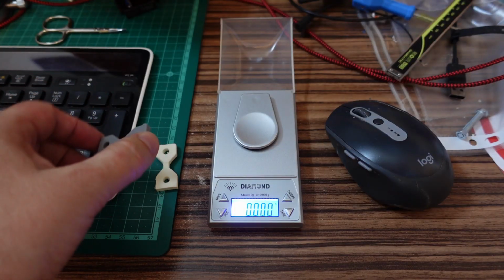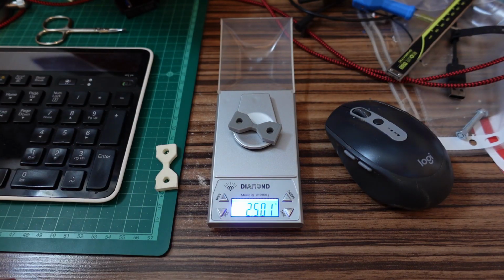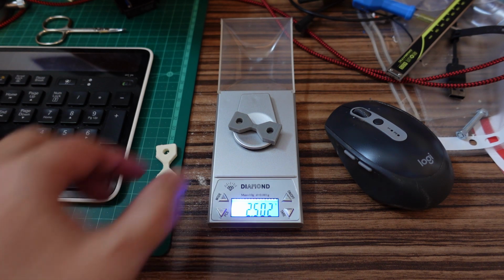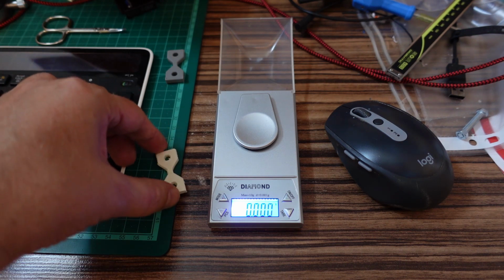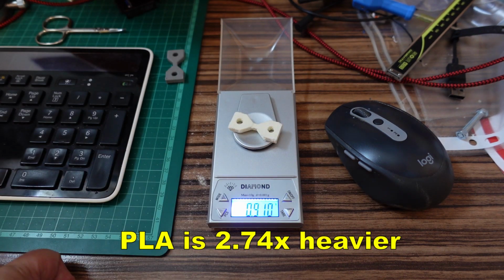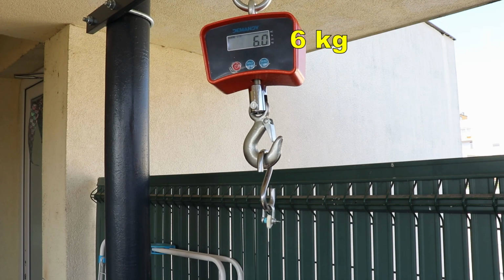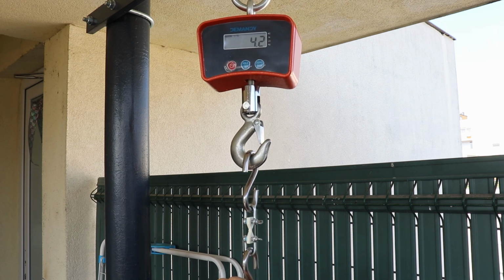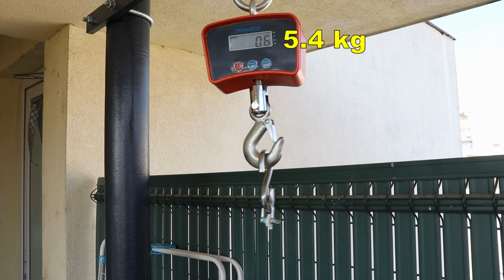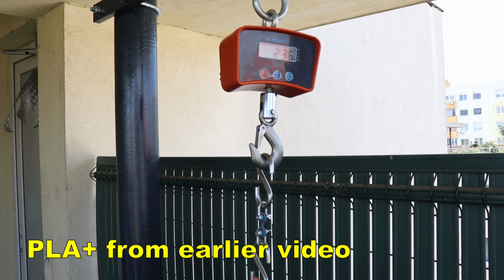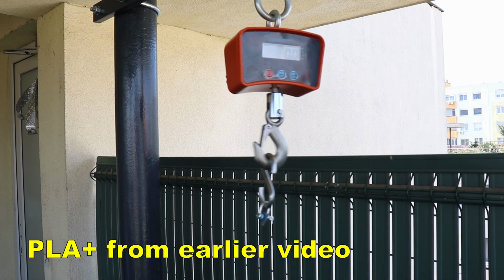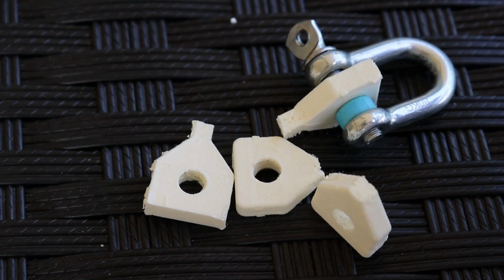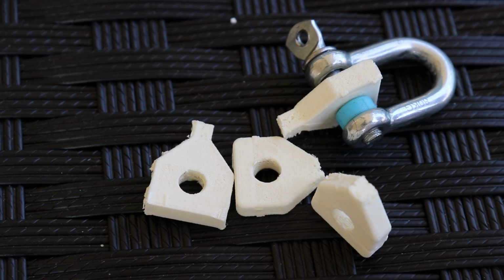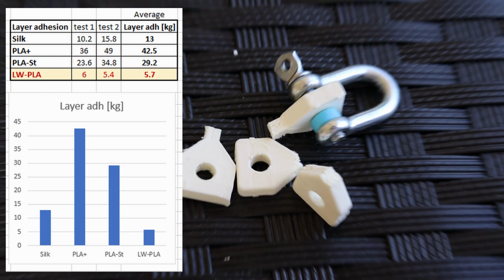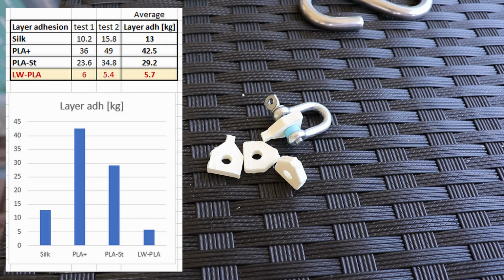And again just a small weight comparison before the pulling test. 2.502 grams the PLA and light PLA 0.911. Well, the layer adhesion actually is noticeably weaker than regular PLA or PLA+. And these are the results compared to the other eSun PLA types.